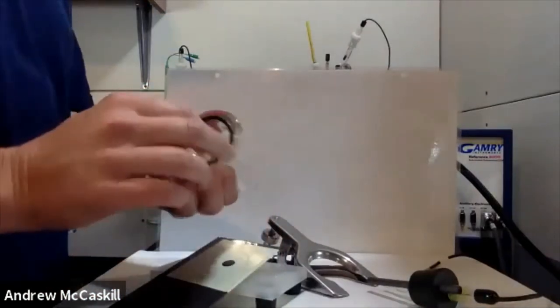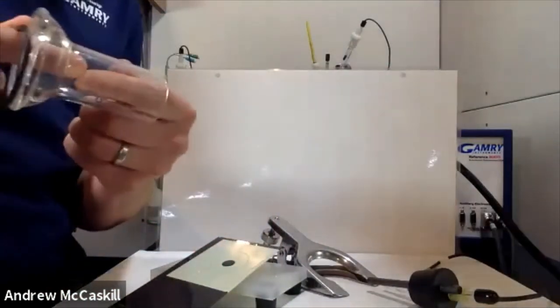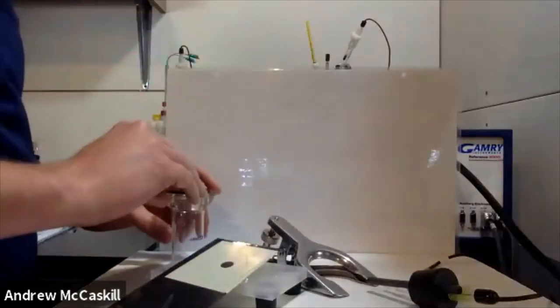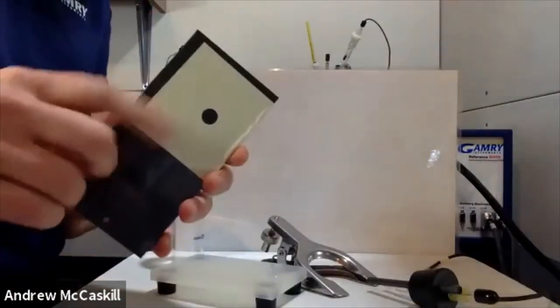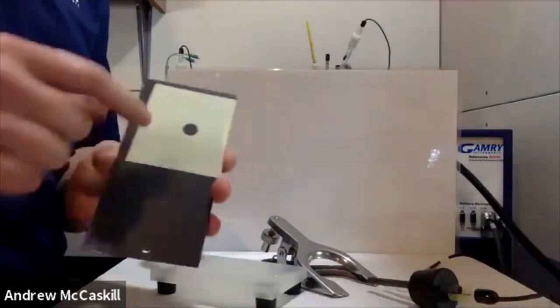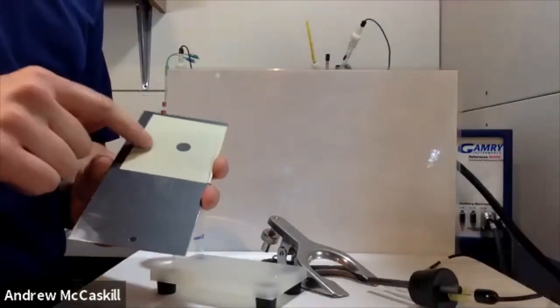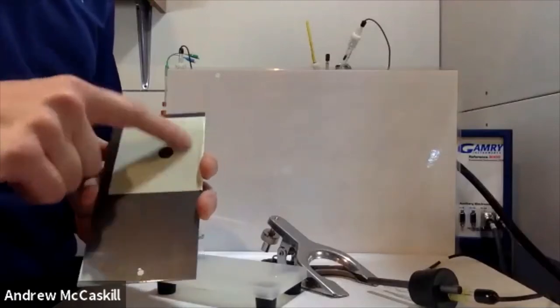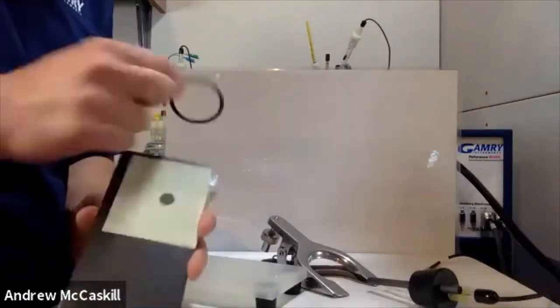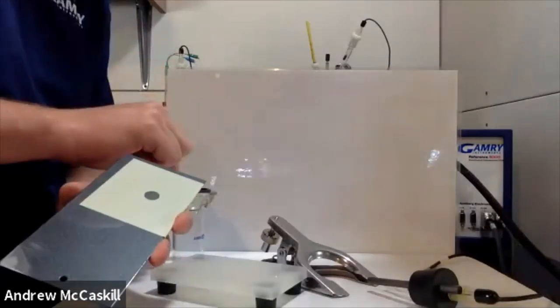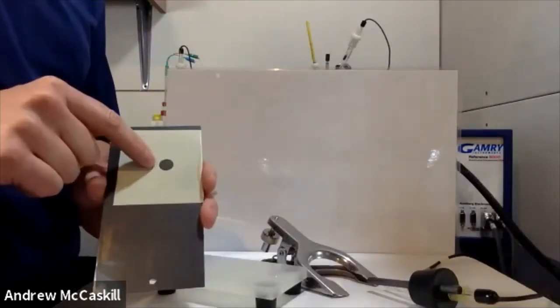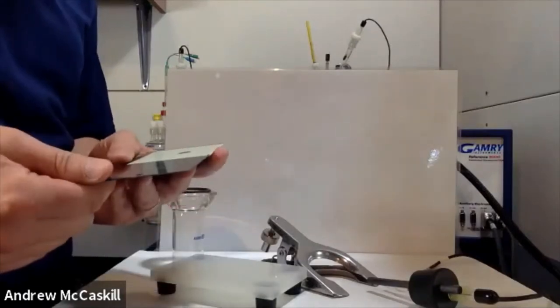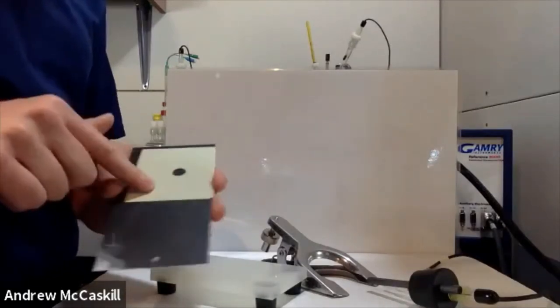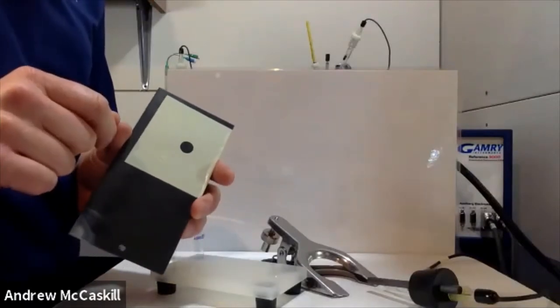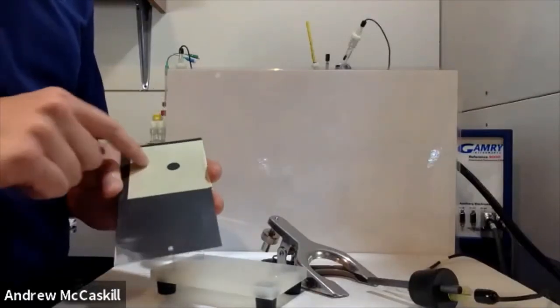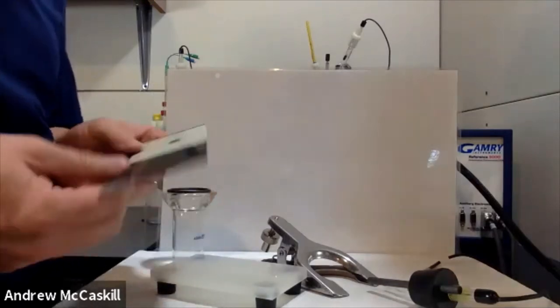So this is just an open-end cylinder, opened on both sides. And the reason for that is that we can expose just this one little spot right here on the coated sample. This is one of our sample masks. The reason that I have this on here is so you can avoid edge effects around where this O-ring makes contact here with the sample. Might also help you get a better idea of the actual surface area you're studying, but these can be really effective if you're noticing a lot of variances in your data, might be because of edge effects around the edge. So the sample mask can be used.